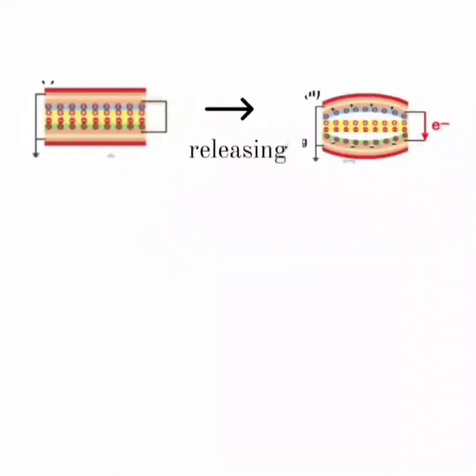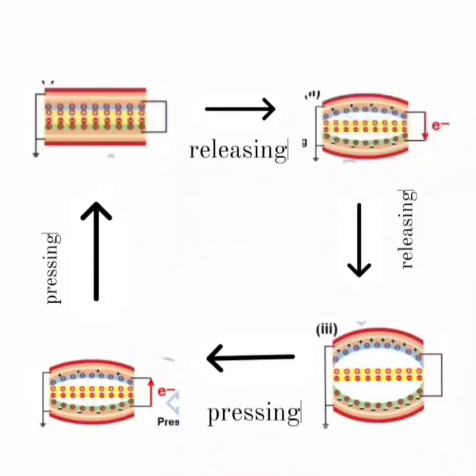For the AS TENG, we can see that when the pressure is retracted, the copper electrode on the back of the PTFE layer will have lower potential than the electrode on the back of the PA layer, which drives electrons to flow from the top arch to the bottom until the pressure is fully retracted and an electric equilibrium is achieved and the electrons stop moving. Once the pressure is applied again and the ribbed tribo layers come closer to each other, electrons flow in the opposite direction, and after that, the cyclic generation of potential difference between the top and bottom electrodes was numerically studied in the COMSOL Multiphysics software.